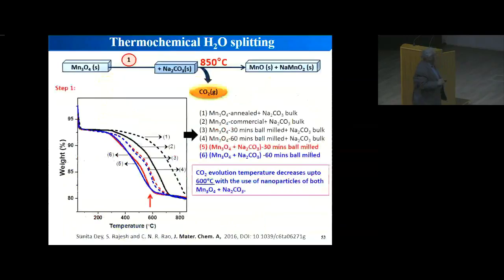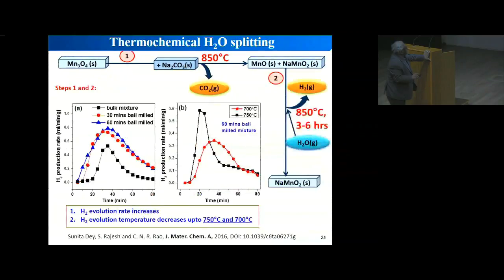And we have shown in Bangalore now, it has just come out in our work, and do the same at 600 to 700 degrees, 750, 700, in my lab you can produce hydrogen. Thermal decomposition at 700 degrees unknown for water. It was always 1,500 to 2,000 degrees. Now, that has now brought down in this multi-step thermochemical cycle to 700 degrees. So, many people have written you can make it into a commercial plant if you like. I'm not going to do that, I'm too old for some young guys somewhere. A lot of people are writing, you know, you can do this process to produce hydrogen.